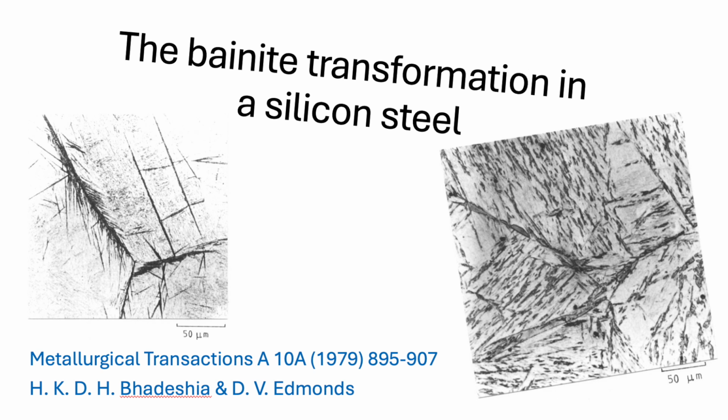Pretty definitively. They took samples that had partially transformed to lower bainite, containing ferrite and cementite, and then quickly heated them back up and upquenched to a temperature above where this supposed eutectoid reaction should occur. And if it was a eutectoid, the cementite should have dissolved back into the austenite phase. Exactly. But it didn't. The cementite remained undissolved. So that ruled out the simple metastable eutectoid theory as the primary formation mechanism for LB. Okay, another theory bites the dust.